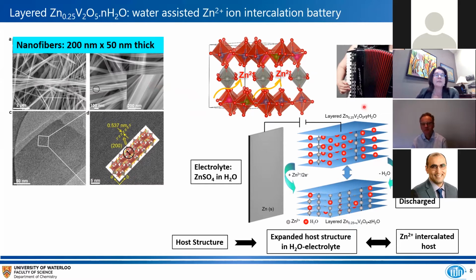And this is important because this cell relies on the incorporation of zinc into this already slightly zincated material, in which a lot of zinc is incorporated. And it does so by pushing out some of the water between the layers. We call this a water-assisted process. And it kind of functions like an accordion. So when you put these layered ribbons in water, effectively the water puffs up the layers. It allows the zinc to incorporate between them. And as the zinc incorporates between the layers, the accordion sort of pulls shut until finally we have complete discharge of the cell, and on recharge, the reverse process occurs. So the water actually assists, at least in the initial stages, to allow the migration of zinc between these layers.